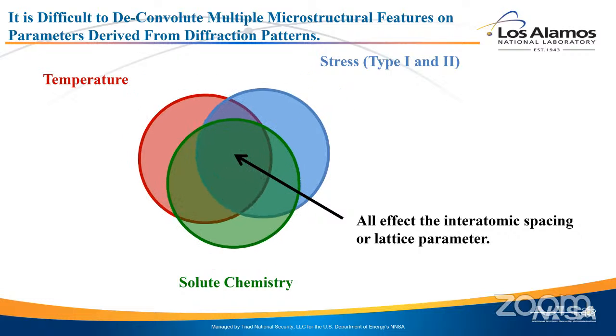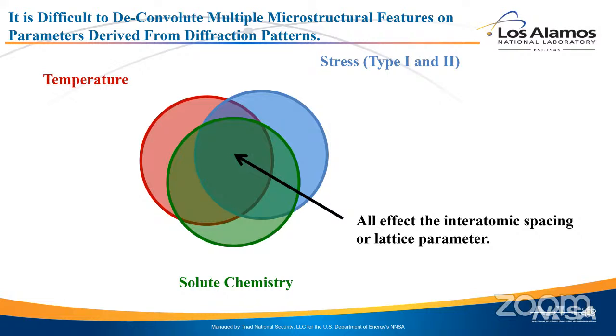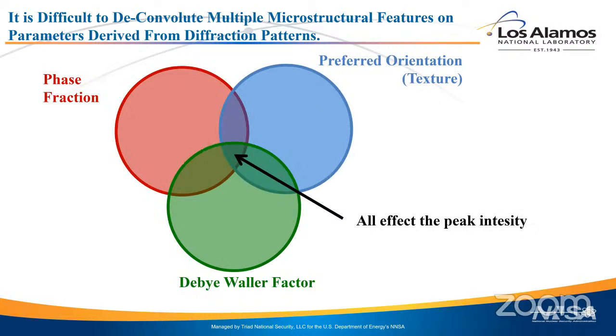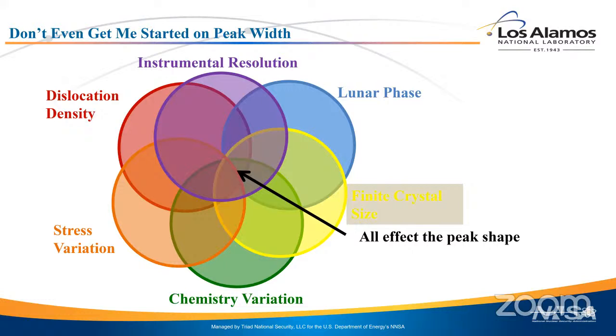If you go into some of the other features, the peak intensity, it's the same thing. Phase fraction will affect the peak intensity. Preferred orientation will affect the peak intensity. One a lot of people ignore is the Debye-Waller factor. If you change the temperature, that will affect the peak intensity. Those things, again, are all convoluted. If you go into peak width, this is where things really get hairy. A lot of times, people will interpret peak width in terms of microstructural features like dislocation density or coherent crystallite size, but there are a lot of things that can affect peak width.